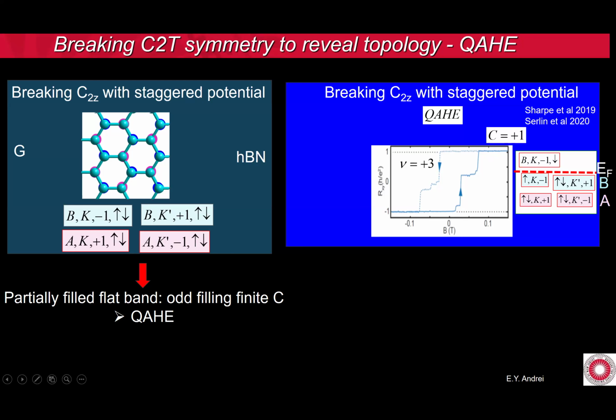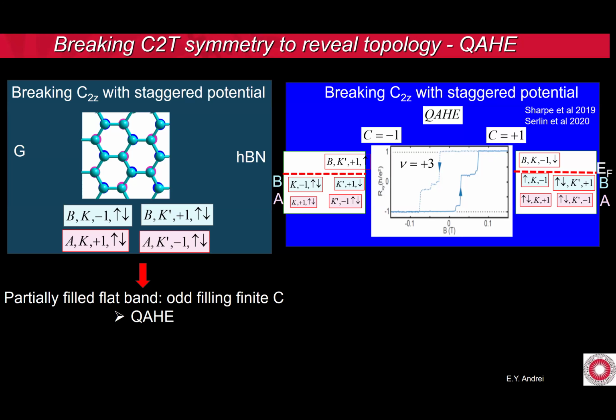You just add up all these Chern numbers, and this is what they did. And then you come back with the field. There's a hysteresis here. So at 0 magnetic field, it is still a Chern number of 1. You overshoot, and then it's going to sit in the other valley, and you get a Chern number of -1. So that's what you're doing. Now, if you hadn't applied the magnetic field, they could be in different parts of the sample, they could be Chern number +1 or -1. You wouldn't see anything. You need a magnetic field in order to see that.